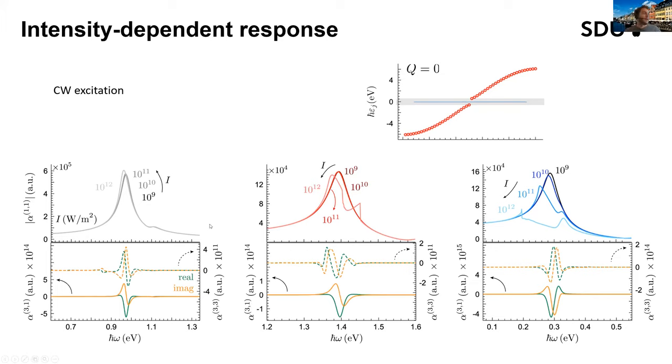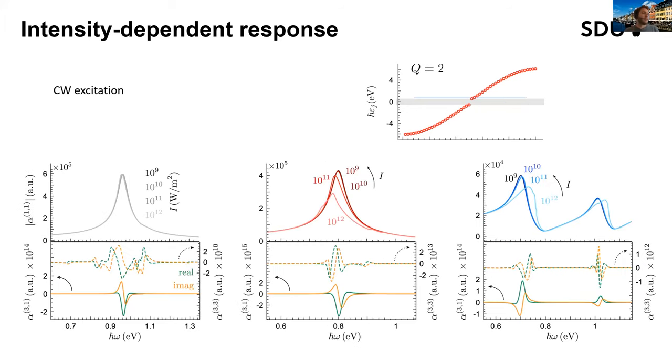insulator. And this behavior is qualitatively described in the perturbative simulations if we look at the response associated with the Kerr nonlinearity. So this allows us to predict which way the peak will shift, or whether it will dominantly saturate or shift. And through doping, we can either enhance this or make it worse, actually, depending on how we do things. So we have a lot of tunability here to think about how to optimize plasmonic saturable absorption, for example.